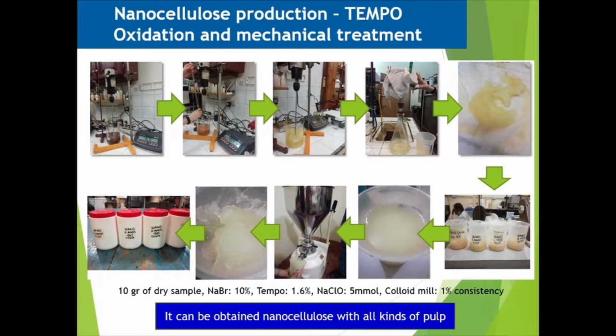We choose a chemical pretreatment of TEMPO oxidation and then mechanical nanofibrillation in a colloidal mill. The TEMPO oxidation conditions for 10 grams of dry sample were 10% sodium bromide, 1.6% TEMPO, and 5 mmol sodium hypochlorite. First, the sodium bromide and TEMPO were dissolved for half an hour, then the pulp and sodium hypochlorite were added, maintaining a pH of 10 to 10.5 with the help of sodium hydroxide. When the pH is kept constant without using sodium hydroxide, the reaction is over.